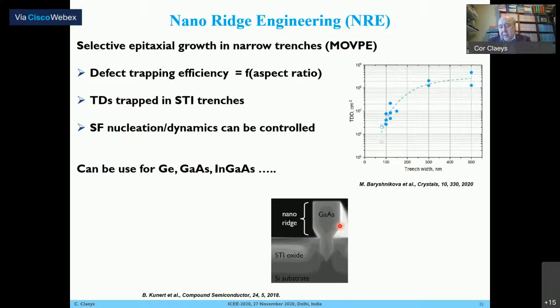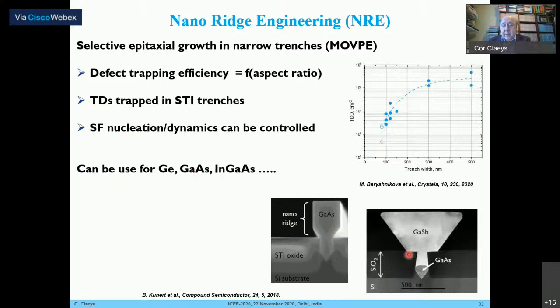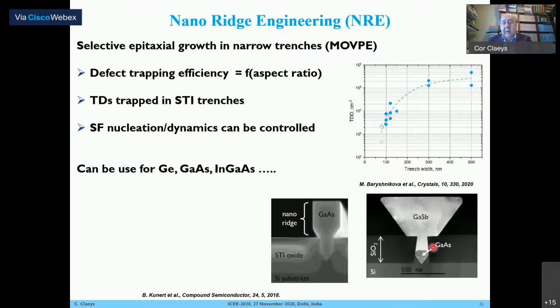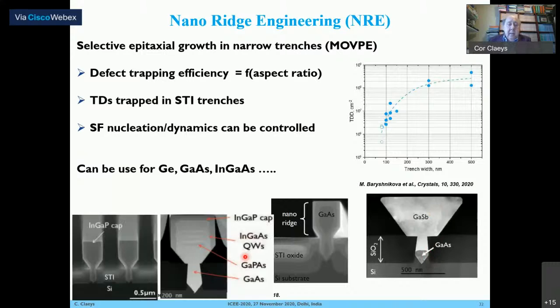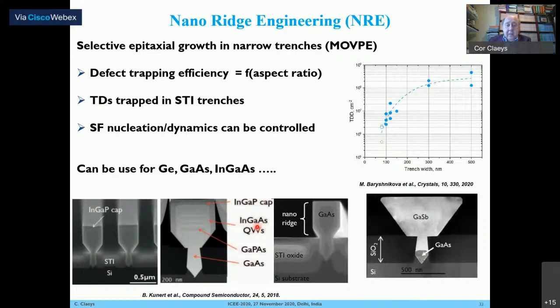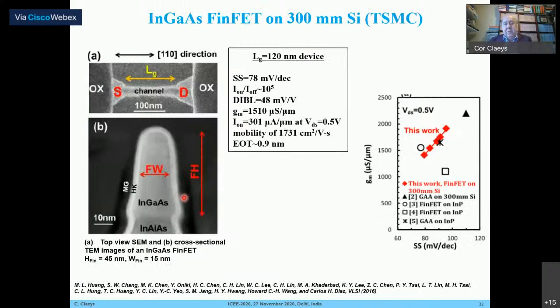Here you see an example of gallium arsenide on silicon, an example of gallium antimonide on gallium arsenide on silicon, and a final example where we have indium gallium arsenide on silicon. And on top we have an indium gallium phosphide capping layer. So at the recent conferences, very excellent performance has been reported. And here, for instance, you see an example of an indium gallium arsenide FinFET on 300 millimeter silicon wafers.